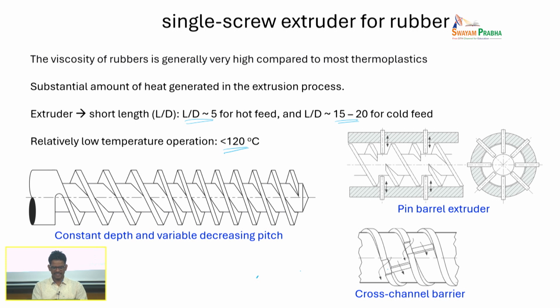This is an example of an extruder for rubber. If you see here, unlike the single screw extruder for thermoplastic where the barrel diameter was constant and the diameter of the screw changes from one end to the other, okay. But for extruding rubber, you don't change the diameter of the screw, the diameter of the screw remains the same, but you see the pitch, which is basically the distance between two subsequent turns, keeps diminishing as you go down, okay.